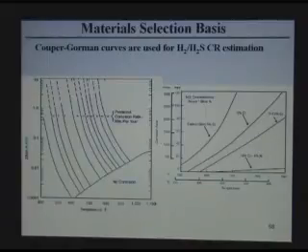And as you see here, carbon steel, this is a summary. Carbon steel gives you the highest corrosion rate. And as you go by alloy, 9 chrome is less, 13 chrome is less, but stainless steel is very low. So usually in such a system, you switch from carbon steel to stainless steel because the difference between these other materials is not much. It doesn't save you much.